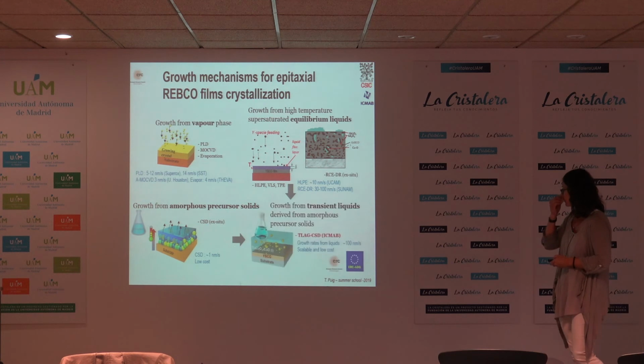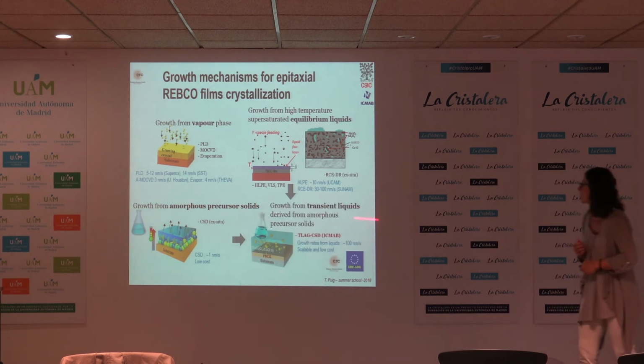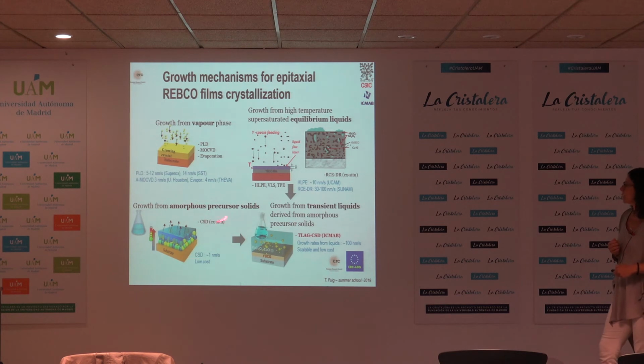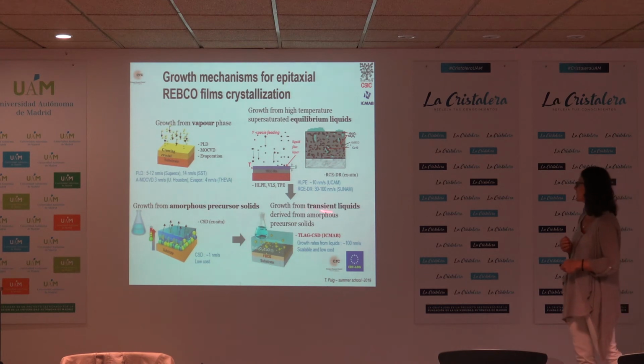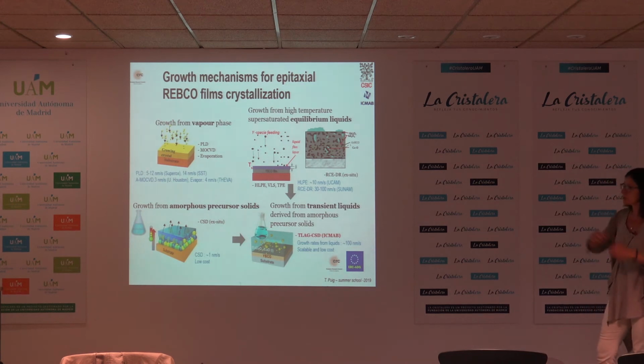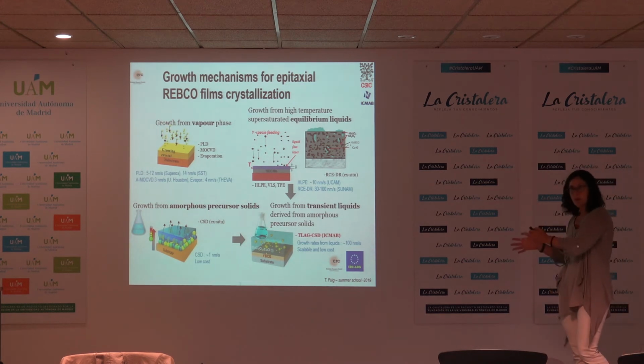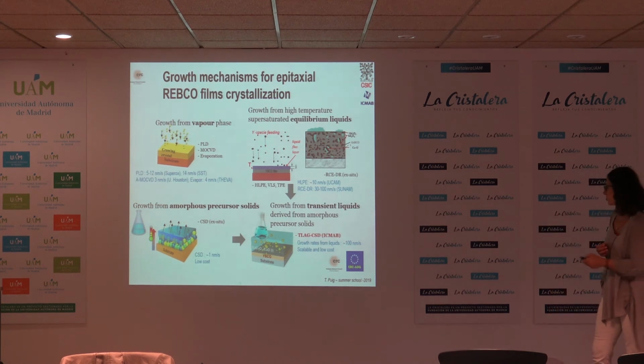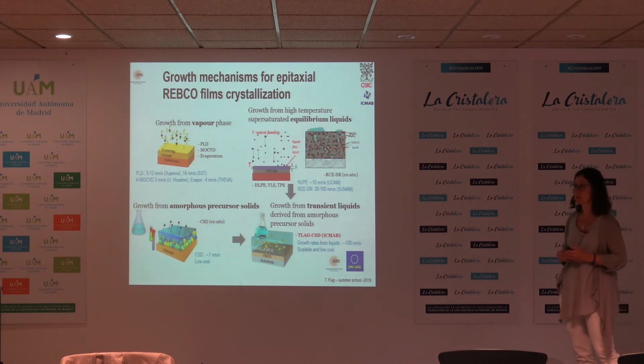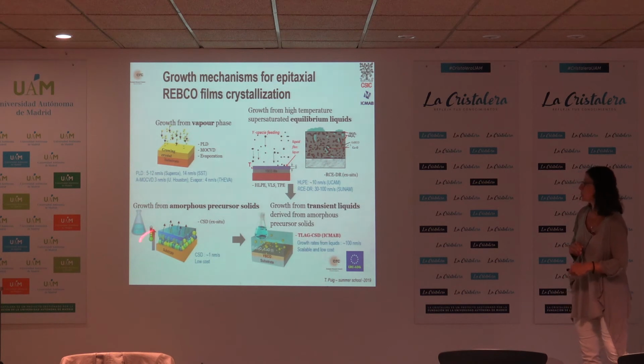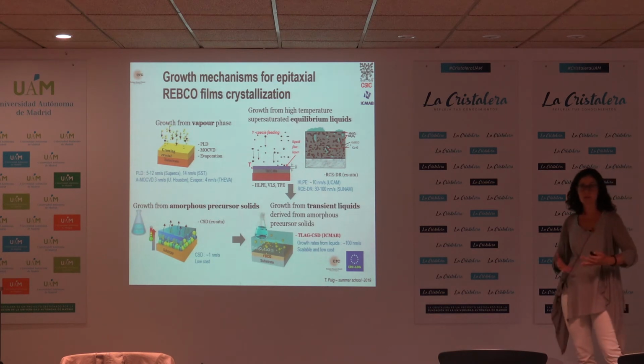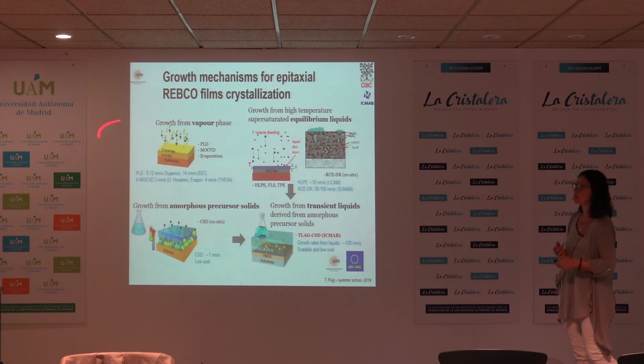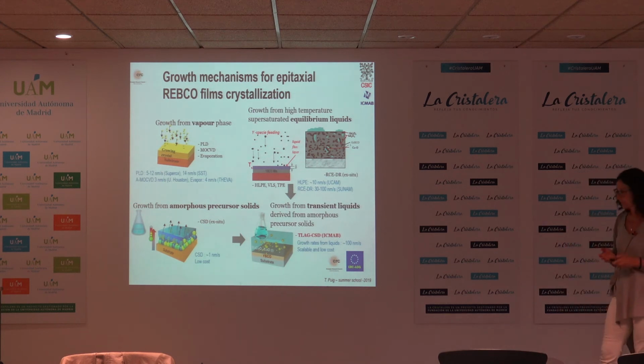So what we proposed in our case was to use the CSD advantages and the liquid advantages and try to define a new process which we have called transient liquid assisted growth, that allows us to grow after the pyrolysis from these nanoparticles to the YBCO through a transient liquid. Okay, and I will just be showing. And this we have been able to demonstrate, that we can grow then at 100 nanometers per second, which is 100 times higher than what we had with CSD, but with a low-cost process of chemical solution deposition as compared to pulse laser deposition or other vacuum techniques.